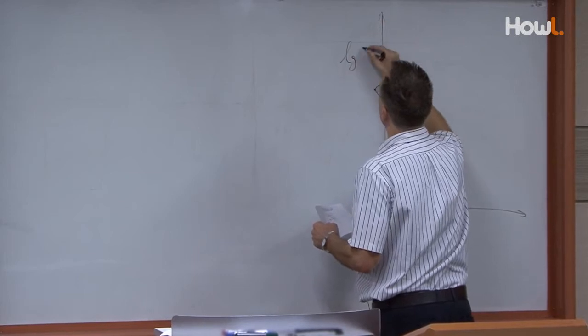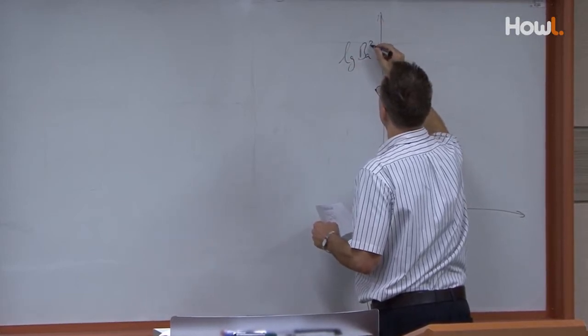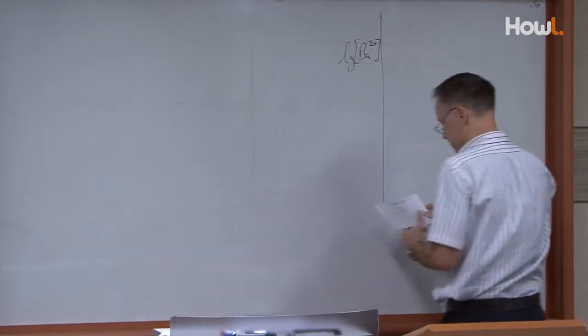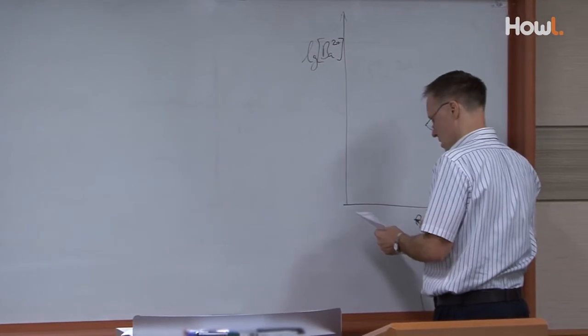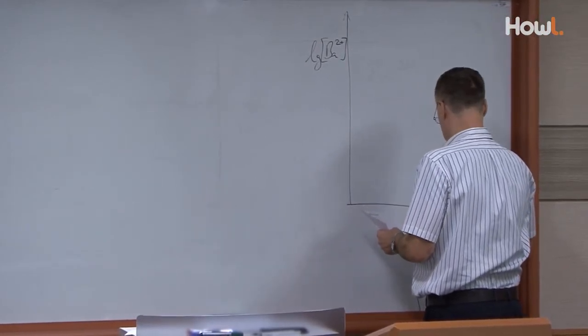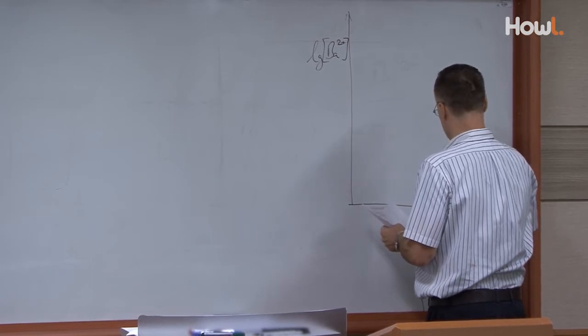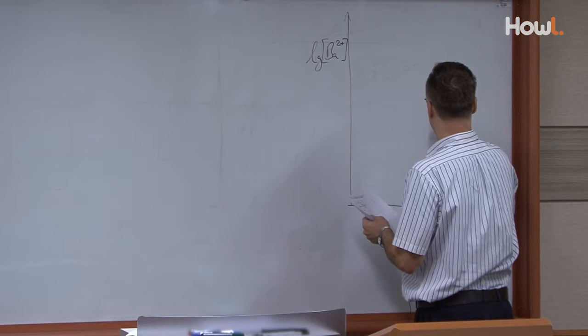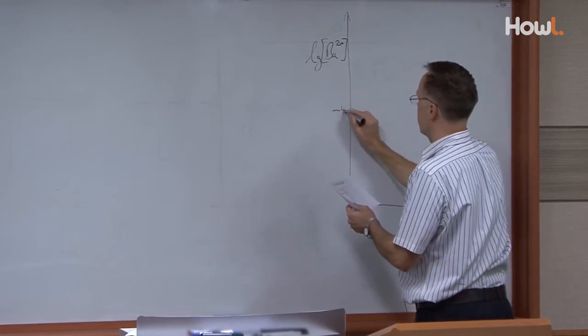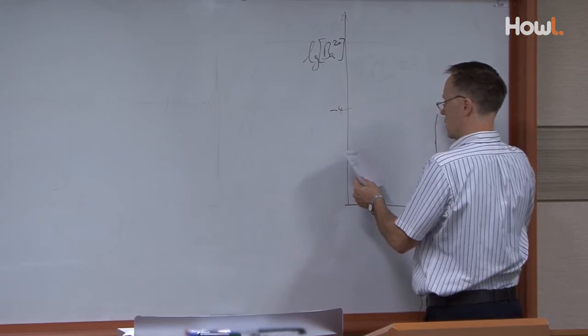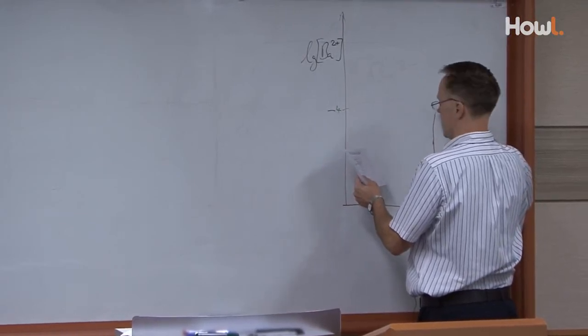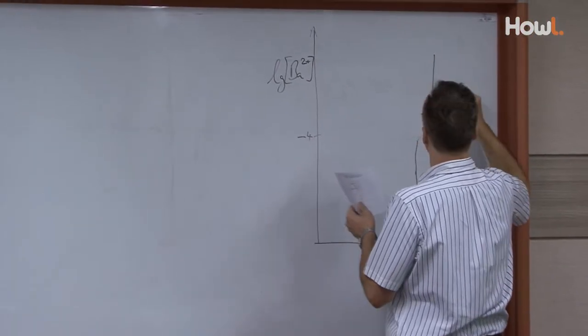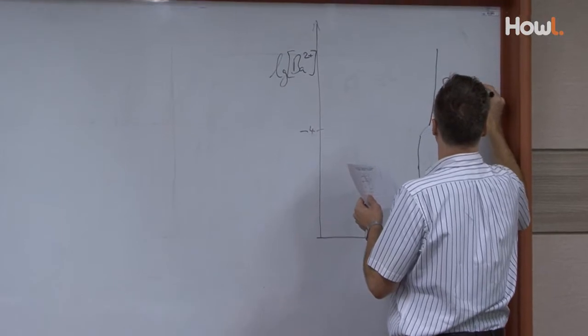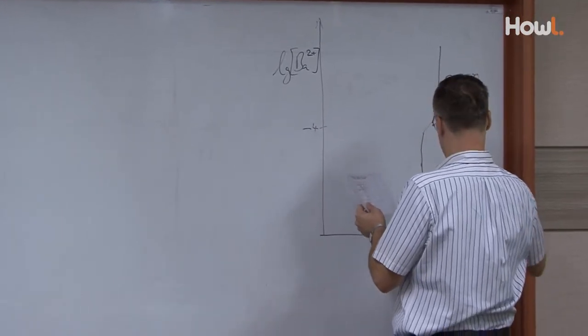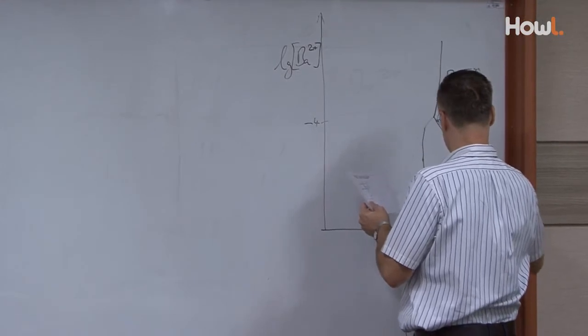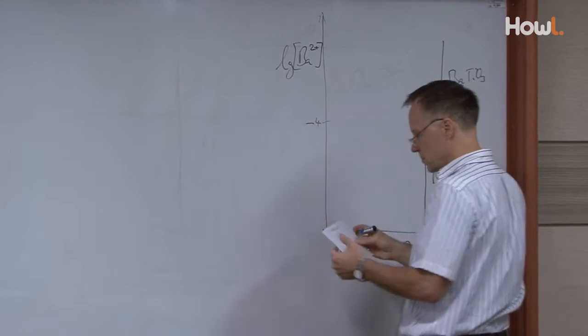So here's a log of barium ions concentration. And here we have pH scale. And at about 11.5 here, this is where vertical line goes up. And then at -4, so 10 to -4 mole per liter, this splits up a little bit like this. And then up here, here is barium titanate. Here is barium hydroxide, plus.